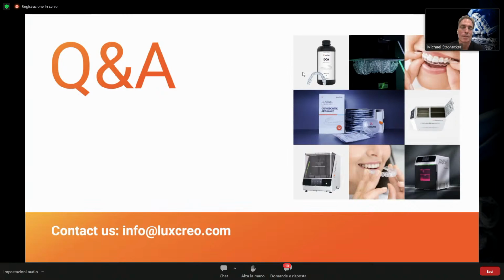And what that ends up being with the resin cost, the resin is on a per aligner basis, like I said, dropped from $4 to $5 down to $2 to $3. That was mainly from using a lot less support material. With Lux Creo, we always go conservative to ensure accuracy, safety and efficacy, and then we refine from there. We've got enough data now over the past year to reduce the support structure by 60%. So we're at 40% of the original support structure approach, and we went from 6 to 16 per build. So you get more per build and a lower cost per aligner.